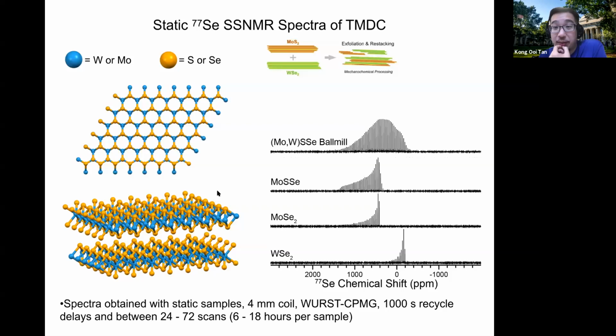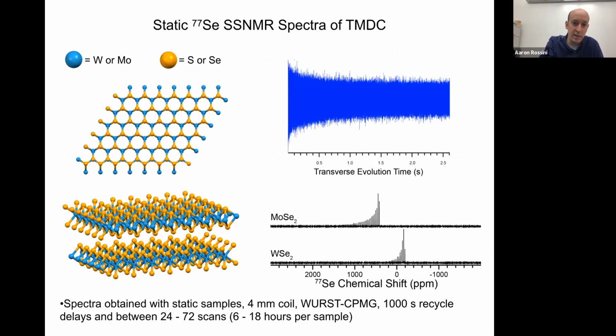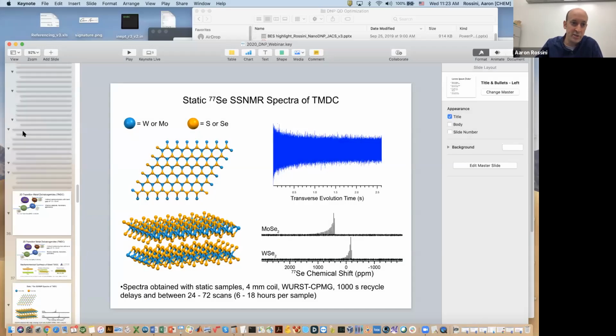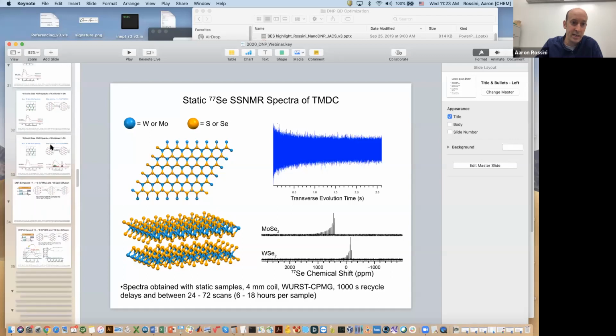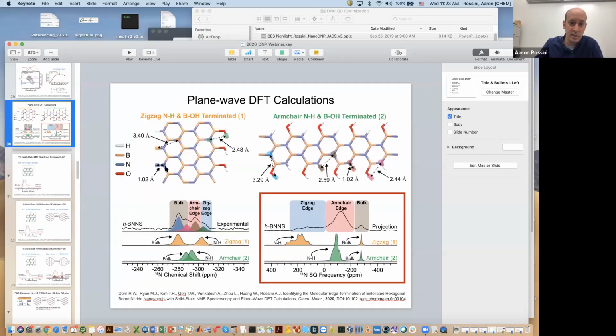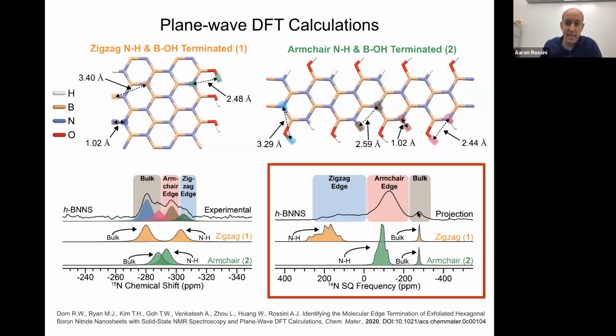Is the first order quadrupolar coupling for 14N of hBN an issue for you to study? No, the bulk 14N nitrogen CQ for the bulk sites in hBN are actually quite small. So the bulk site has a narrow peak. The CQ there, I think, is only like 200 kilohertz. These edge sites have quadrupole coupling constants, I think, between 1 and 2 megahertz. And those are pretty easy to study with HMQC techniques.